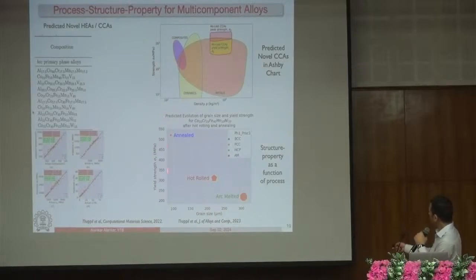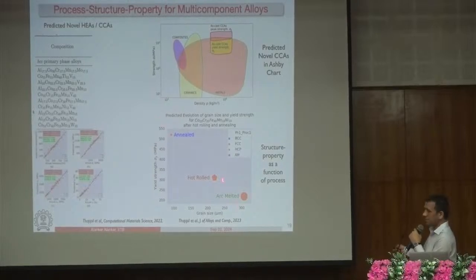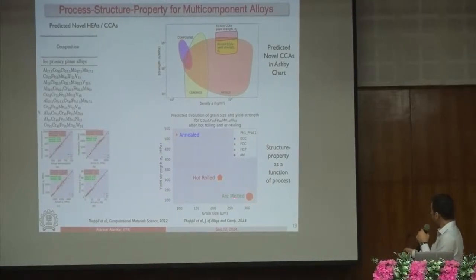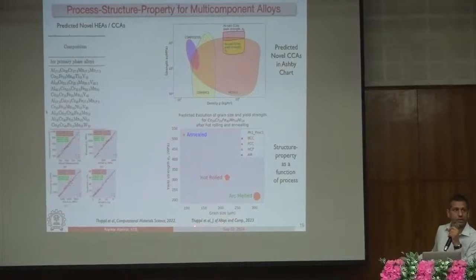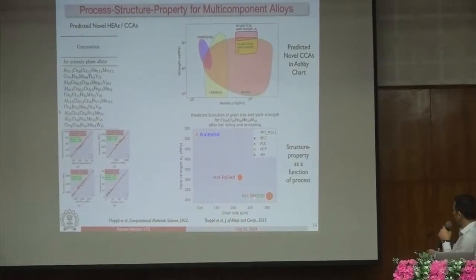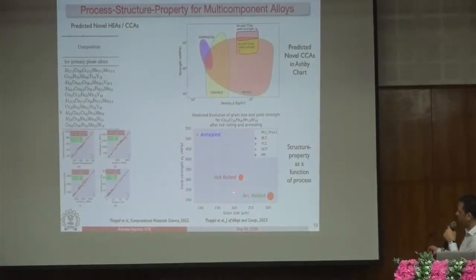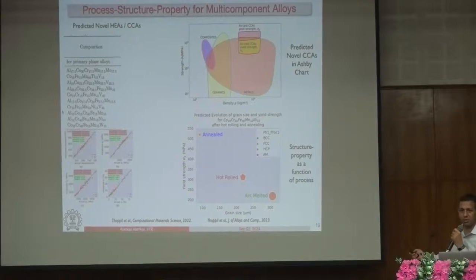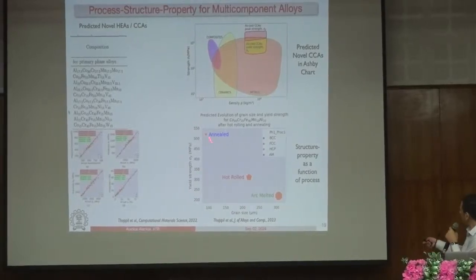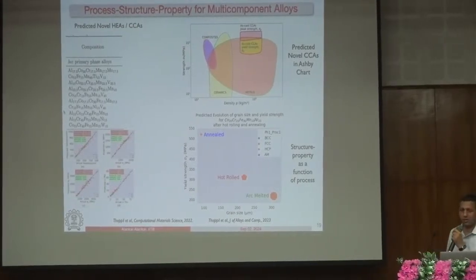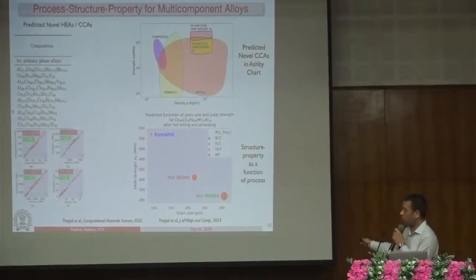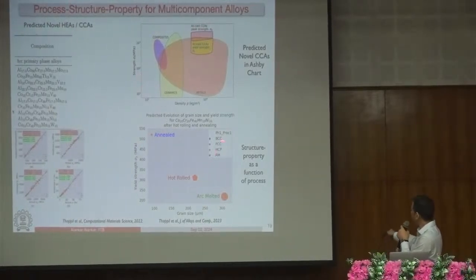We were able to also correlate how the yield strength changes as a function of grain size and processing. So for example, if you just arc melt a metal, it is supposed to have much larger grain size. Solidified metal has large grain size, and thus it has also lower hardness and lower yield strength, right? If you deform it, the grain size will reduce. So hot rolled material usually has lower grain size than that. If you roll it further and anneal it, the grain size will reduce and strength will increase. All that we are able to capture as a function of phases.